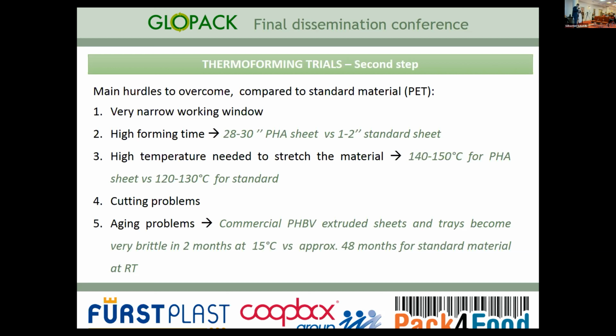Another issue that we found was about aging problems. This material, also the different grades that we got from Fraunhofer, has the problem of aging. It means that after 2 months, the material was not possible to use anymore, because it became more brittle than before, and it was also not possible to stretch it during thermoforming. And 2 months is quite a short period. Also, the storage of this material was done at a lower temperature, 15 degrees, to avoid the aging, or to make it slower. But 2 months was the maximum time that we were able to use it.